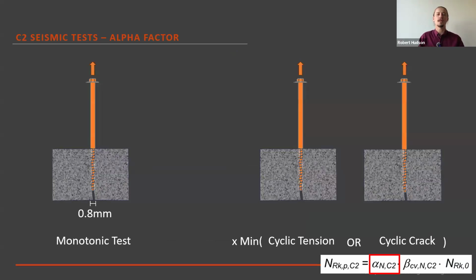Now, the alpha factor is trying to represent the loss in load carrying capacity from each of the mechanisms that I showed before: your cyclic tension loading on the anchor, the additional wide 0.8mm crack width, and the cyclic crack behavior around the anchor. The formula for C1, by the way, is exactly the same. It's just accounting for fewer mechanisms.